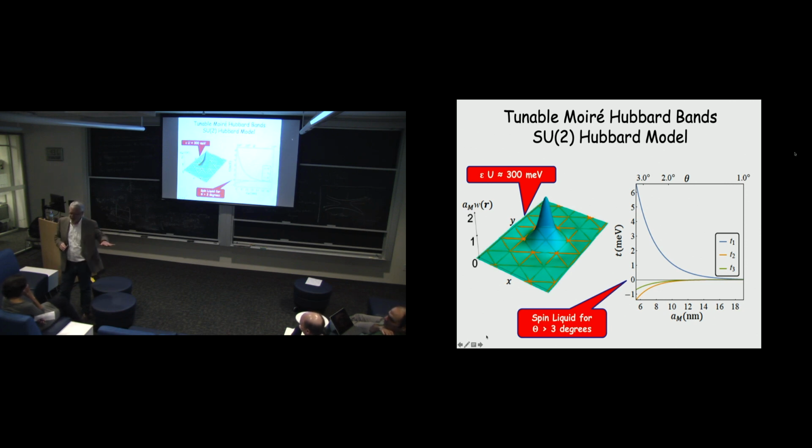Pick up one half, set it on the other, twist it by a controlled amount, and try to put it down as flat as they can. Right. And it turns out that when you make a Moiré superlattice, after you put it down, it kind of gets stuck. It's important that it gets stuck because the lowest energy configuration is actually for it to realign.